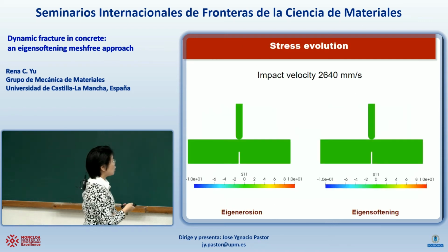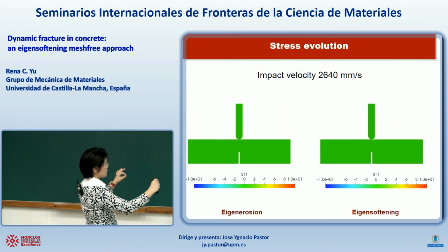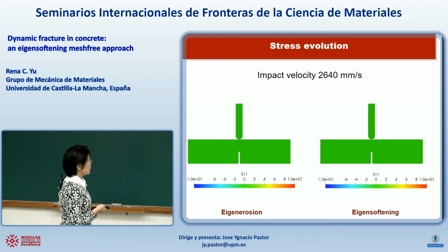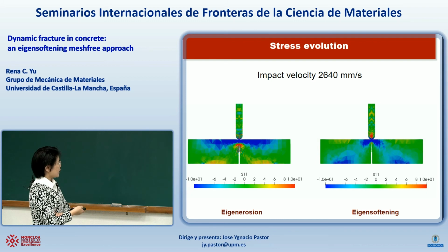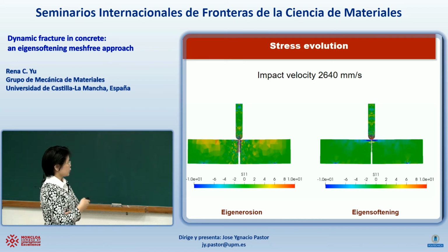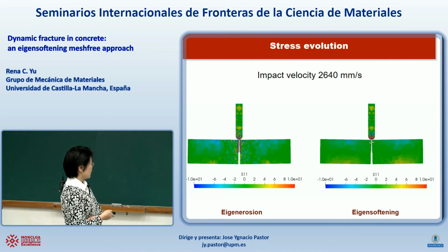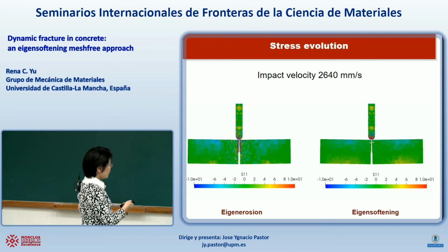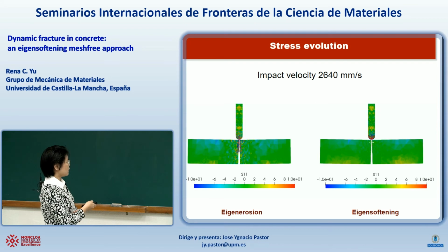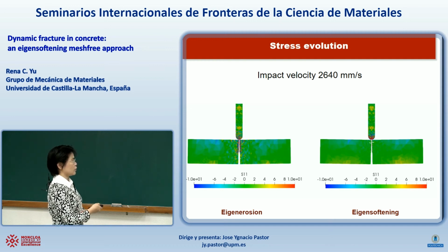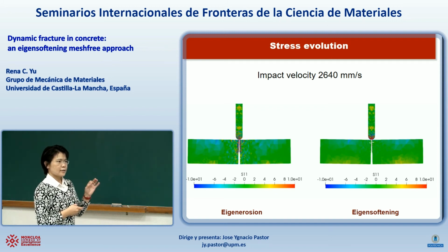And if we look at a video of the stress evolution, for the stress S11, the horizontal direction. Let's see if it works. On the left side, you have the eigenerosion approach. On the right side is the eigensoftening approach. What you see here is that we use a maximum of 10 megapascals and a minimum of minus 10 megapascals. But I'm going to show more that if we use eigenerosion, we always have a bigger area of stress concentration. Actually, the maximum would reach around 50 to 60 megapascals. I forgot to say that the tensile strength of the material is 5 megapascals.